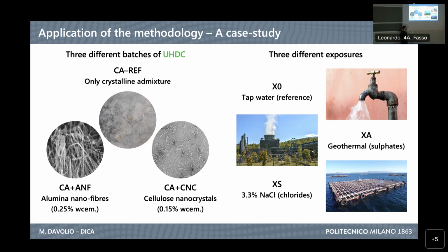The first one is tap water used just as a reference, but what we know is that our structure, for example, in this case, a geothermal plant, is exposed to sulfates, and this is a raft for mussel farming, which is exposed to chlorides inside seawater. So we studied these 2 exposures. I want to mention that for geothermal water, we shipped the real water from a geothermal plant to the laboratory to have it for our exposure.